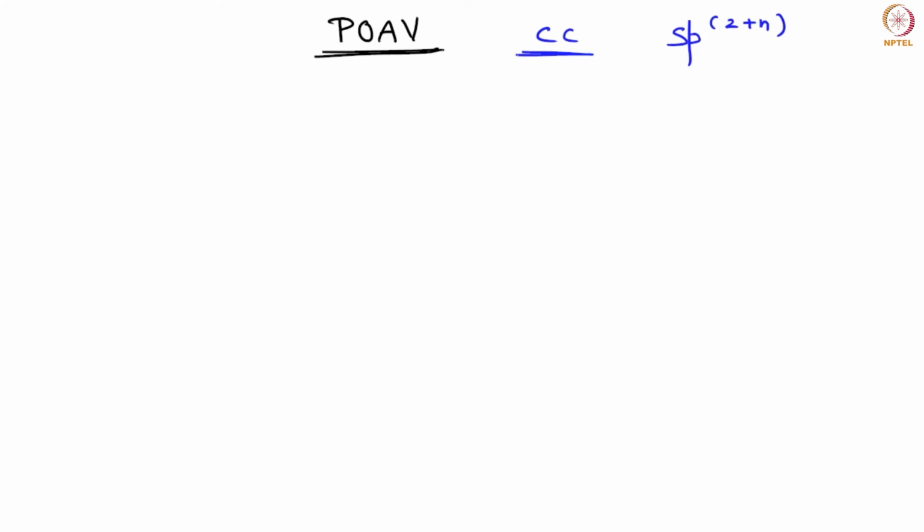It's not just a mathematical numerical average of sp2 and sp3 type hybridizations. I will give you an example in the case of C60. We have also discussed this in class. 101.6 degrees is your theta sigma pi. However, the hybridization is sp2.28. So from here itself, you can guess that the hybridization is not just a direct average.